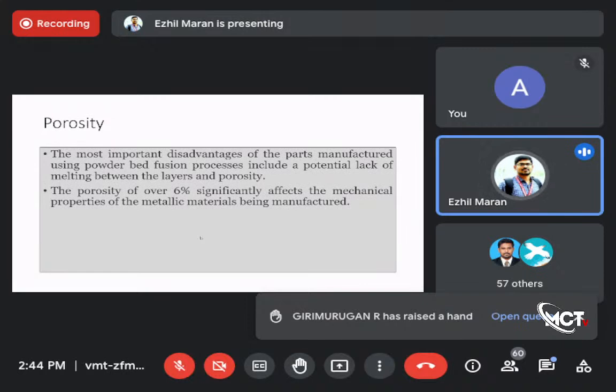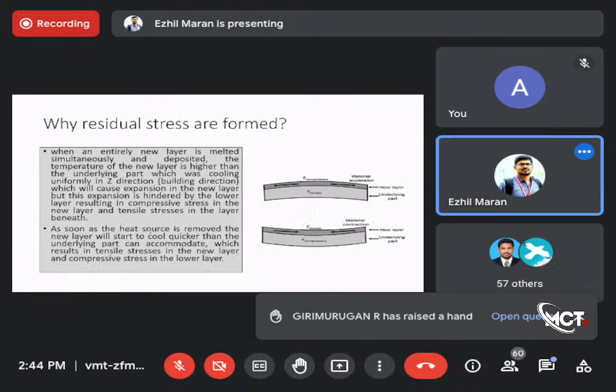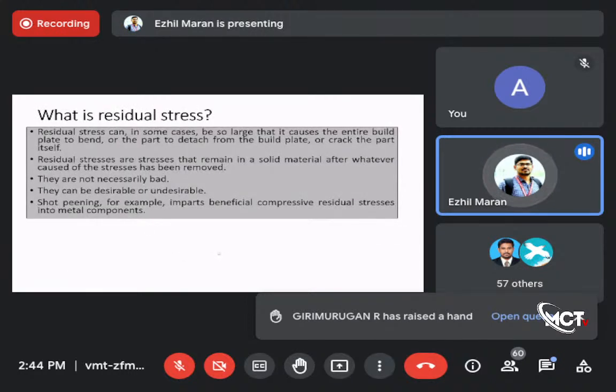A part which contains more than 6% porosity, certainly the mechanical properties are not as good as what we expected. A porosity of more than 6% in the product is generally not recommended. Mechanical properties certainly will be down. Mechanical properties refers to strength, mechanical strength, fatigue properties. Everything will be affected by means of this porous structure. Generally, the porosity should be kept minimum. And the second most important is residual stresses.